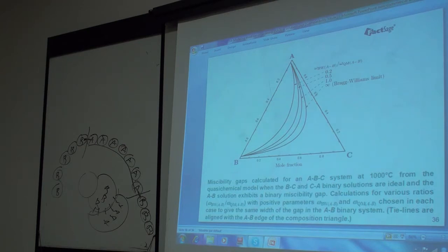Now we can talk a little bit later about the quasi-chemical model, which is the clustering model, the cluster variation method in the pair approximation. Bragg-Williams is called the point approximation because you're distributing atoms on points. The pair approximation is distributing pairs on pair sites. You can go to higher orders. You can consider quadruplets, groups of 4 atoms or 6 atoms arranged on different sites. And there's a cluster variation method, which I'll talk about a bit later. The trouble is you rapidly get way too many variables, way too many things to try to fit.